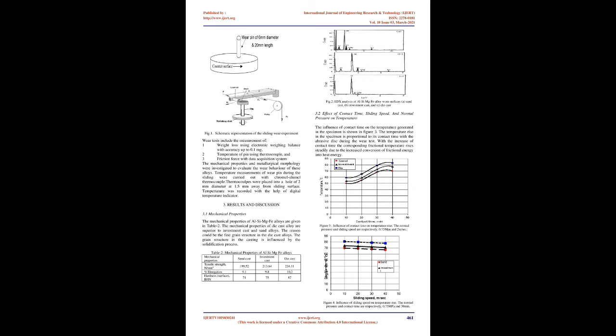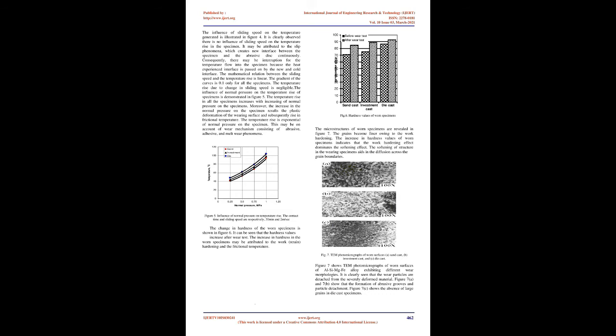The pin specimens were prepared from ALSIMGFE alloys. The dimensions of the specimens were 6 mm diameter and 20 mm length. A pin-on-disc type friction and wear monitor, ASTM G99, was used to evaluate the wear behavior of ALSIMGFE alloys against a hardened ground steel, EN32, disc having hardness of RC62 and surface roughness, Ra, of 0.6.